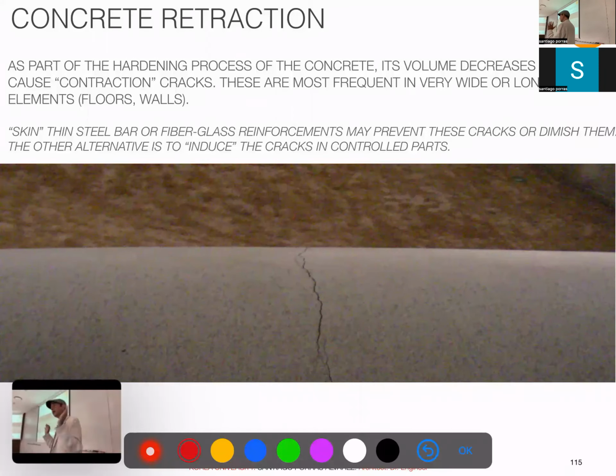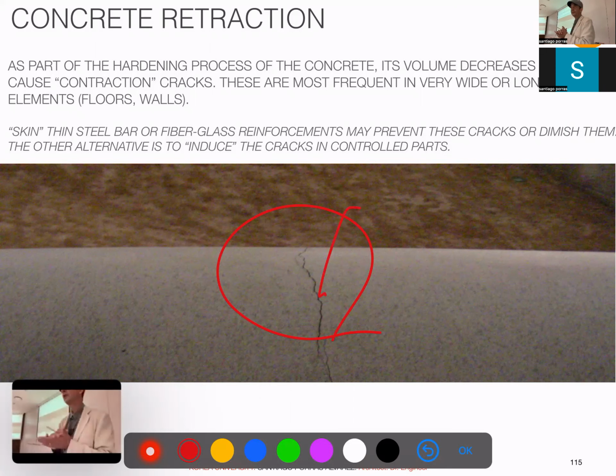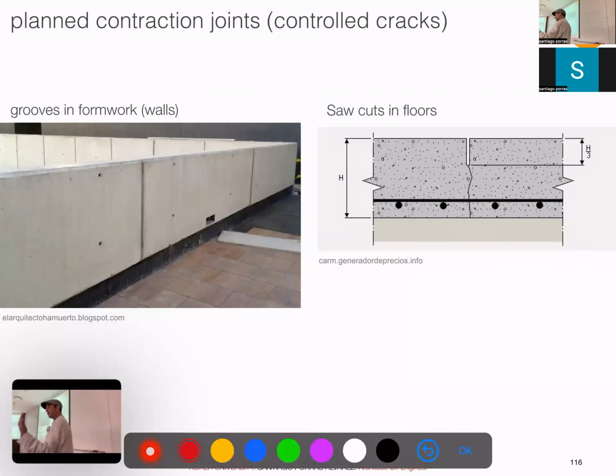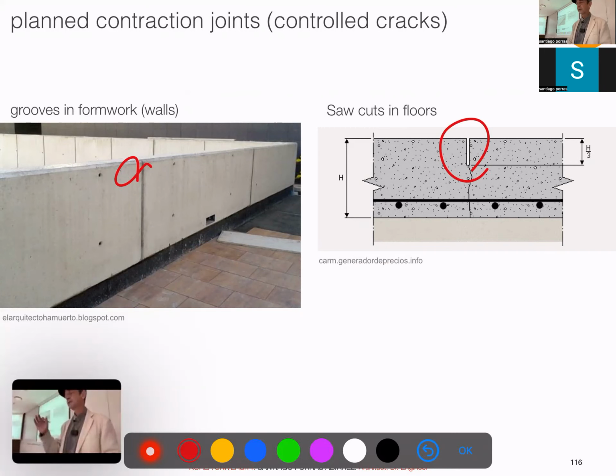Then something that happens in the concrete, in general, is that it shrinks when it hardens. And that is something we have to consider. This is one of the exposed concrete in DDP. It cracked everywhere and people were in panic. They rendered it and it cracked again. So it's something we have to be aware of, right? One thing we do, of course, is that reinforcement will help control those cracks. In very long elements, we usually put grooves, right? So the crack will be more or less where the groove is, if we are lucky, right? This is by experience, and otherwise you will have just the shrinkage cracks and you have to live with them.